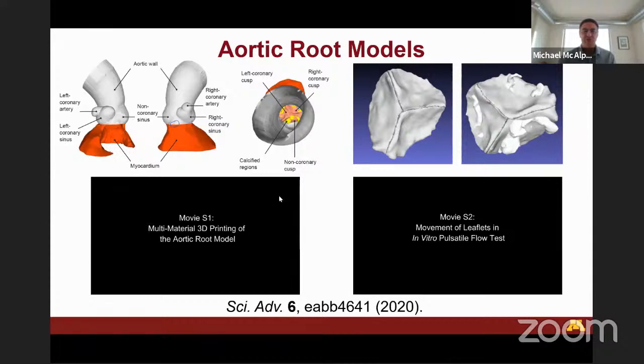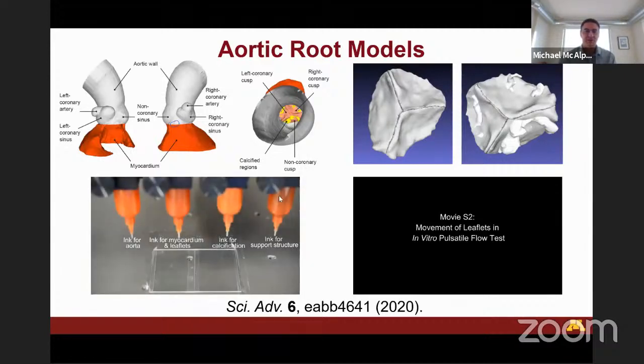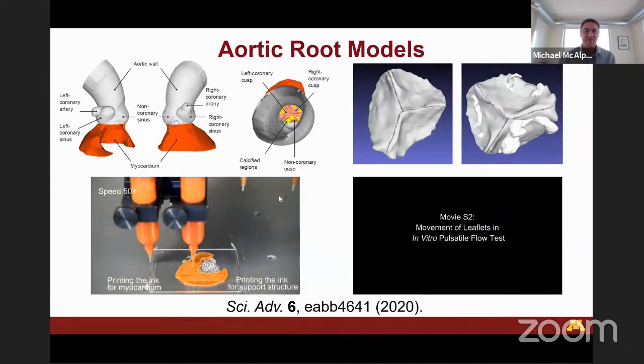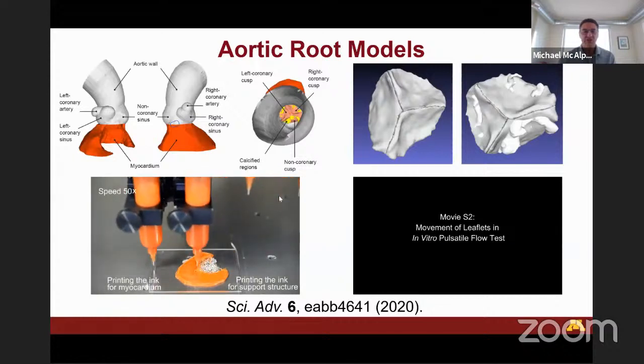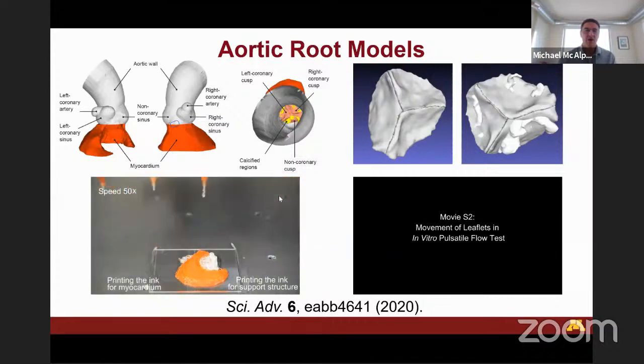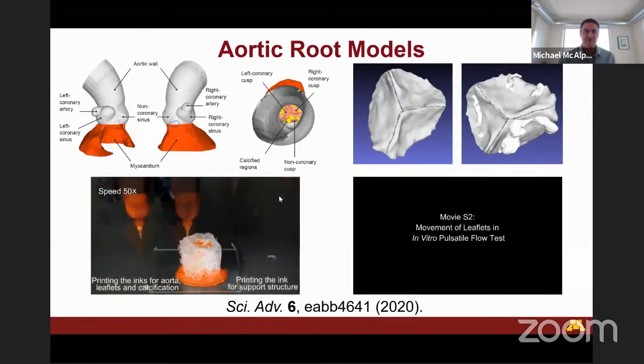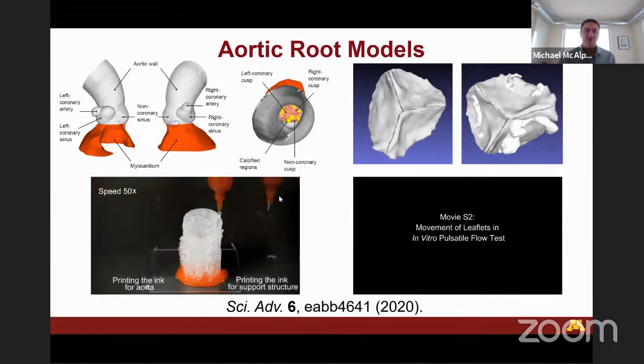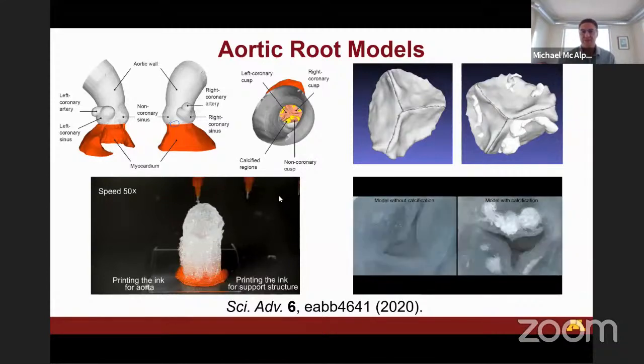So this is a more sophisticated model that we published recently in Science Advances, where we're building multiple inks into the structure. That also includes calcified regions based on a spackling material, where we're replicating the calcification in the patient's aorta in a diseased patient. Now you can see we have inks that replicate the myocardium, supporting ink structures, which is basically a Pluronic that's removed at the end of the process, and we can recreate the leaflet structures. We can create the calcification in this multi-nozzle approach here. And we did see, when we do some of these hemodynamic studies, that the calcified structures do require more pressure than the non-calcified, replicating the patient's disease.